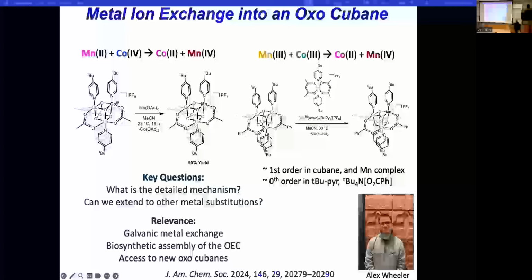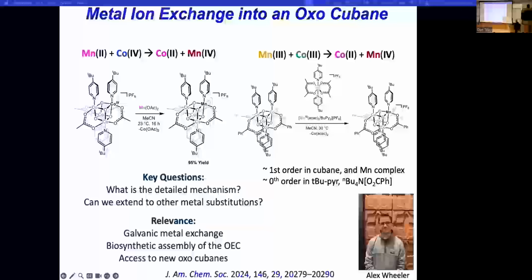Alex just graduated, and he just published a paper on the interaction of manganese acetate with a cubane species, a variety of cubane species, actually. But these reactions are not like the cobalt one that installs a dangler, but rather lead to an exchange of metals in and out of the core of the cube. So you see here that manganese comes in, displaces cobalt, and you get a cubane that we had before, but this is a different way to make it.